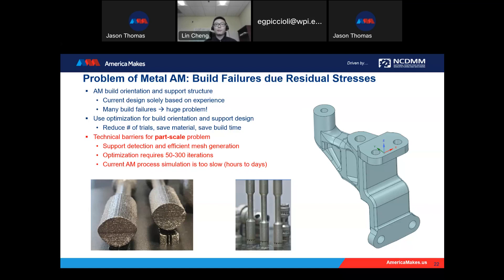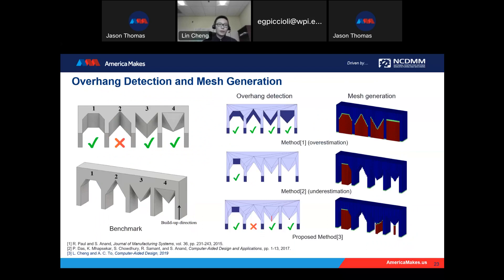We try to develop a method to overcome these barriers one by one. The first one is mesh generation. I designed a benchmark where cases one, three, and four need support structure. For case two, all the overhang surfaces satisfy the overhang angle constraint. For cases three and four, there are overhang edges and overhang points. I tried existing methods — a 2015 paper that generates support structures for all overhang features, which generates too much support that is very difficult to remove, and another paper that only finds overhang facets but ignores overhang edges and points.